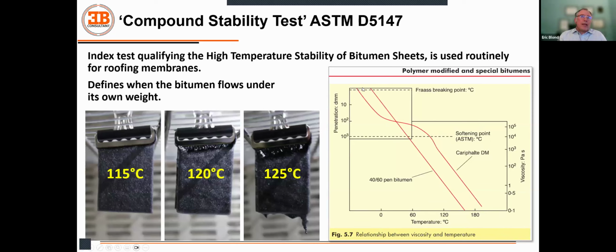On the low end, we can have a product that becomes brittle. Cold bitumen can be brittle like glass, at -30, -40 it's going to break, like pretty much all products actually. On the high end, when you reach high temperature, like 120 something, the viscosity becomes so low that the bitumen can leak out of the product. You can see here examples of the bituminous geomembrane that we tested in this project. At 115, there is nothing really happening. At 120, you can see that the products are starting to separate. And at 125, you can see the bitumen starting to leak. That really reflects how important the temperature is. At very low temperature, below zero, below -20, you can have a brittle product. At +125, it's liquid, basically. So what's happening in between is what we have to understand.